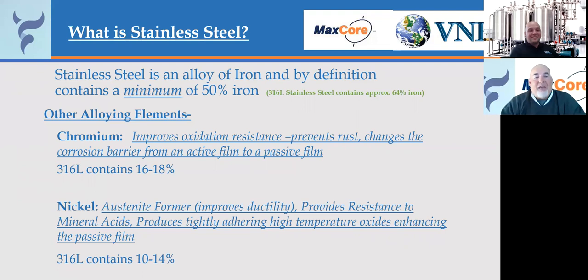So if you look at what the alloying elements are, if you look at the definition of stainless steel, and I know we're running out of time here, you have to have a minimum of 50% iron content by definition. 316 actually has about 64% iron. So what do these alloying elements do? 316L has 16 to 18% chromium content. That improves oxidation resistance, prevents rust, and changes the corrosion barrier from an active film to a passive film.